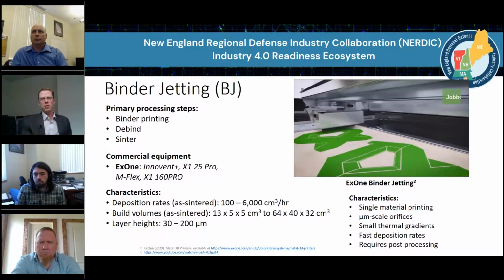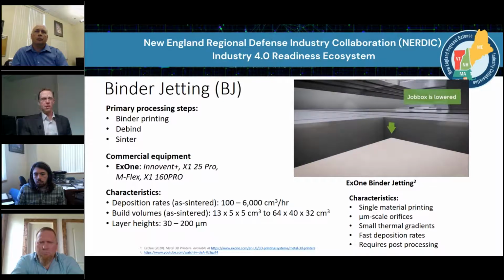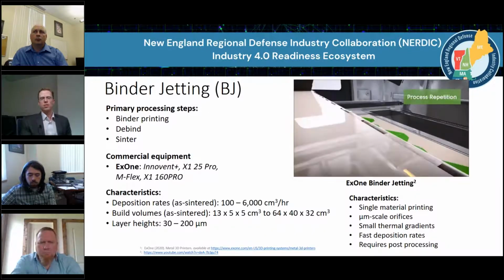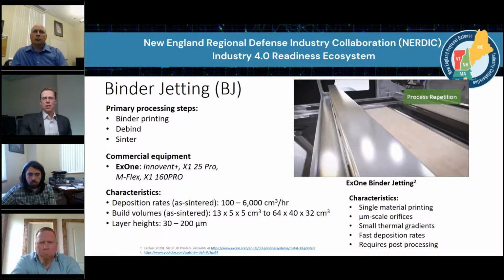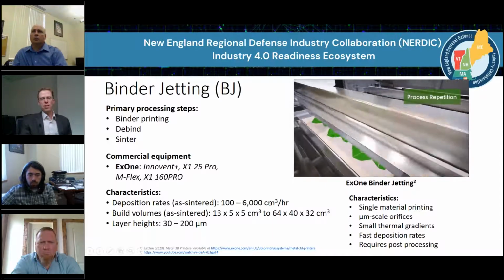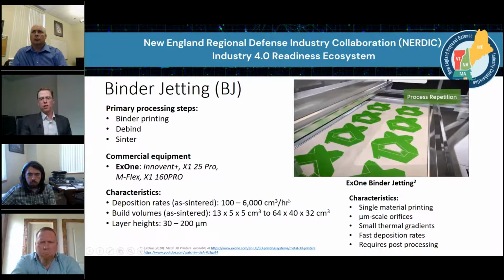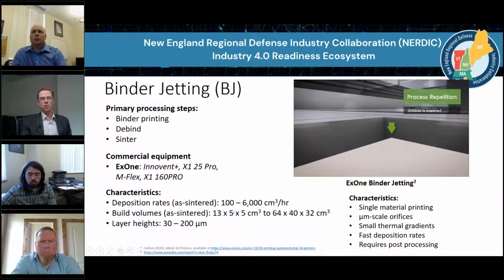Commercial equipment in the space, particularly ExOne, is quite dominant in this space with the Innovent+, the X1 25 Pro, and the X1 160 Pro. Importantly, you see very high deposition rates. If you recall the extrusion, it's about 10 cubic centimeters per hour. Here it is 100 up to 6,000 cubic centimeters an hour, and you can get much larger build volumes. Layer heights are typically 30 to 200 microns, which is similar to the material extrusion. And we end up with